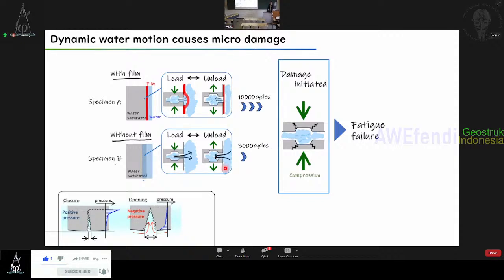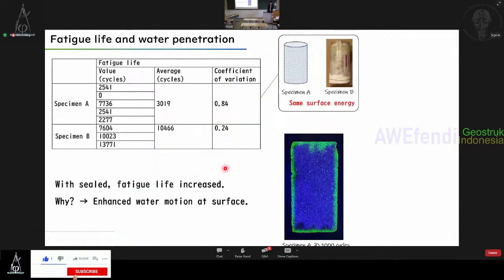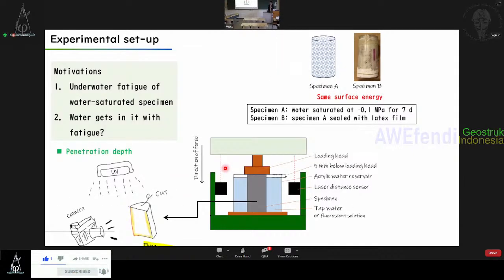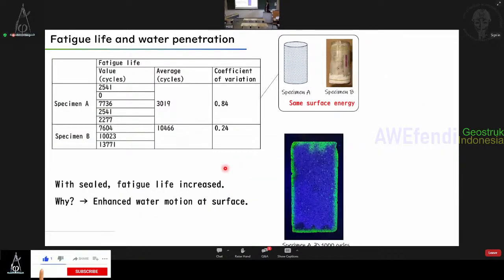And we can see, I think it was in the previous slide, slide 10, we see the green, so we can see water which is on the surface, and perhaps even a crack. Is it two cracks at the top? No, because it's not uniform, this is not a crack, just water penetration. And what this figure shows is not water gradation. This is just showing water motion from inside to outside.